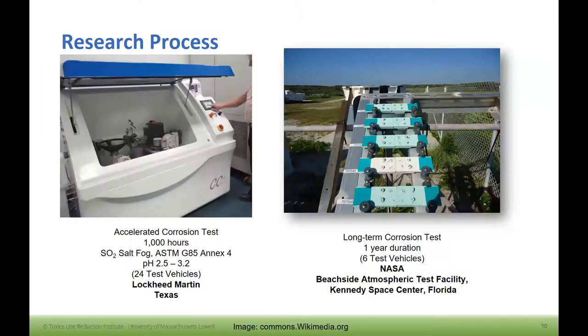Then once the test vehicles were preconditioned, we did some accelerated corrosion testing, which was SO2 salt fog, and that was done at Lockheed Martin in Texas. We also did long-term corrosion testing where they're exposed to an ambient environment, and we did that at the Kennedy Space Center with NASA down in Florida. We did that for a 1-year duration.